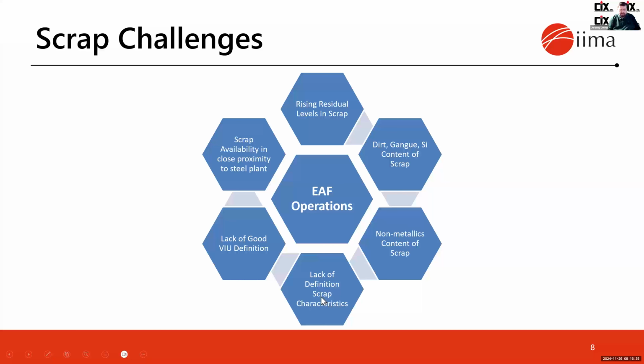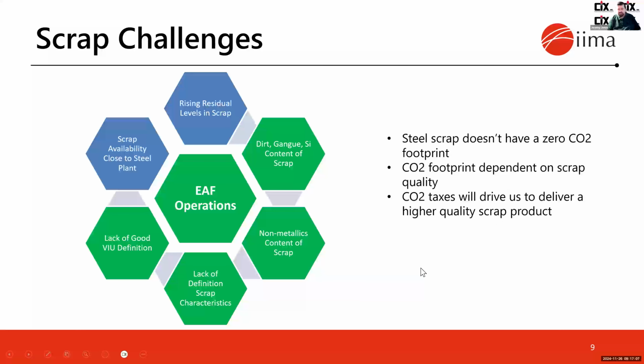We have a lack of definition of scrap characteristics. We tried to address this and have actually defined a global matrix of scrap equivalencies, but there's still work to be done there. There's also a lack of good value and use definition, and again, we've tried to address this within CIX with some of the tools that we've developed. And more importantly now, scrap availability in close proximity to the steel plant, because if you're transporting scrap great distances, there's a carbon footprint associated with that. So here in green, you see the things that we already have a pretty good handle on. Still need a little bit of work, but you see the two that we haven't resolved yet.